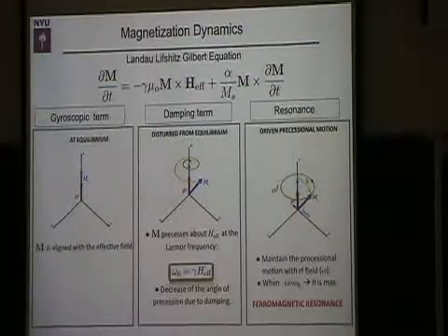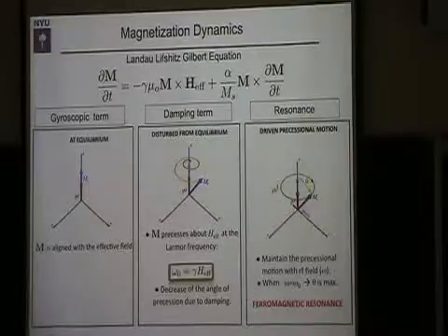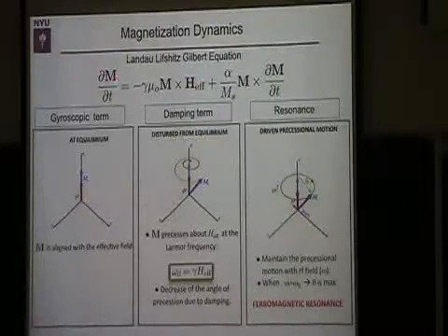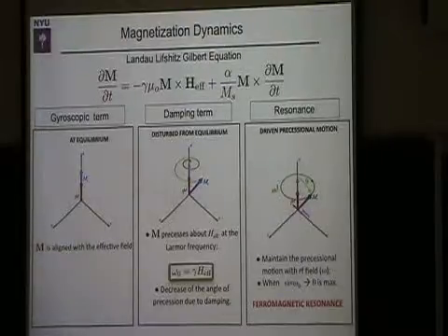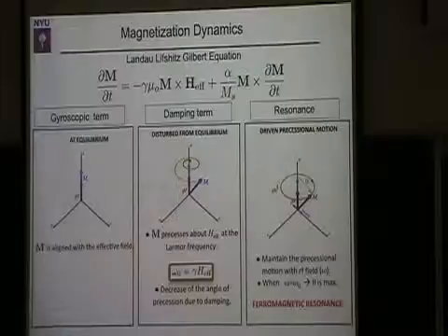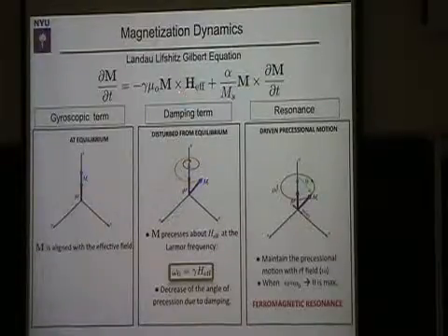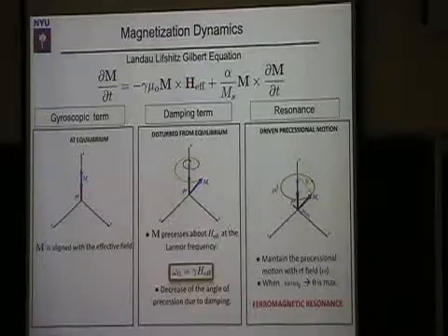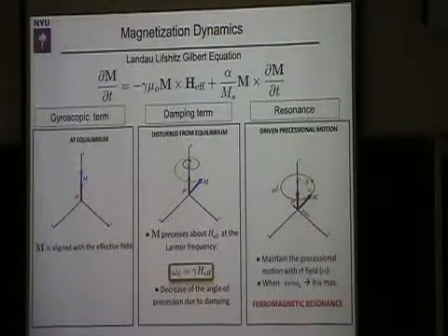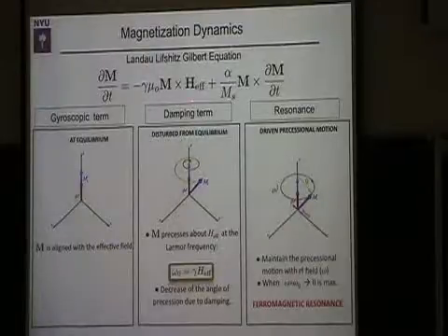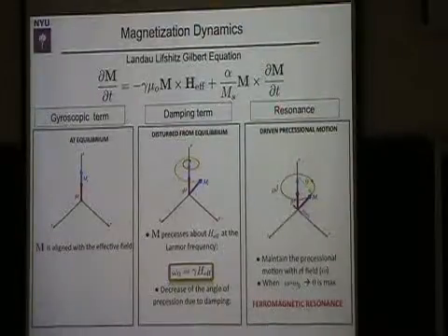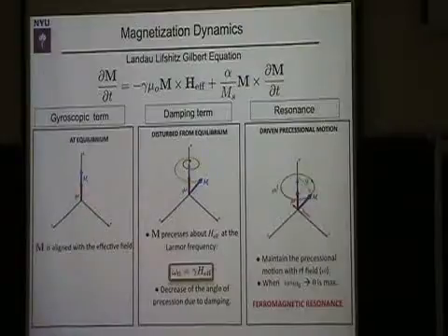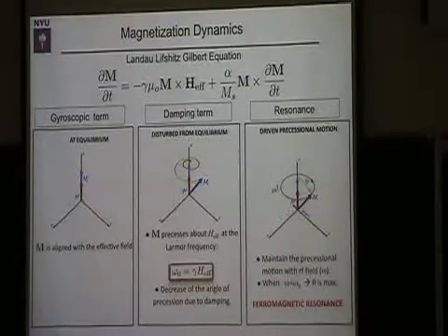If you want to understand the problem of thermal activation, you have to put noise into this expression. You have to put in the coupling to the environment. So we're imagining a very low T, well below the ordering temperature, and it's common then to assume the magnetization is fixed but can just fluctuate in direction. And to describe thermal activation, you can put in a random field. Where is the barrier? The barrier comes in through the derivative of the energy with respect to magnetization. So the dynamics is determined by where the barrier is in this expression.